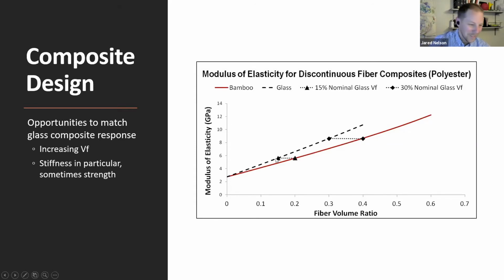I get excited about this stuff. If we have 15% glass fill, we can get a similar stiffness response by bumping it up to a 20% bamboo fiber fill. Similarly, if we look at a 30% glass fill, we can get a similar modulus of elasticity by bumping it up to just over 40%. These are attainable numbers. These are not unrealistic values that we can achieve.